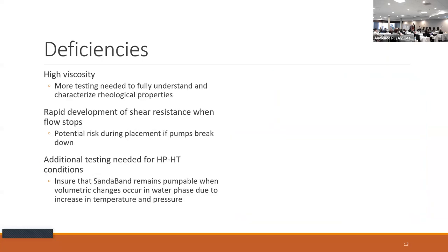The challenges: it's high viscosity. Probably needs to be studied a little bit more, especially at higher temperatures. I think there may be some unique things going on with the thermal expansion of the water and the solids. I want to make sure that on the way down it stays fluid in a particular case, but that can be looked at pretty easily. Another, I don't know if it's a deficiency, but once you stop moving it, it develops shear resistance rapidly. So failure is not an option, and shutting down the pumps during displacement is also not an option. Additional testing is needed for HPHT conditions to ensure that this material remains pumpable when volumetric changes occur in the water phase, which I guess I just mentioned.